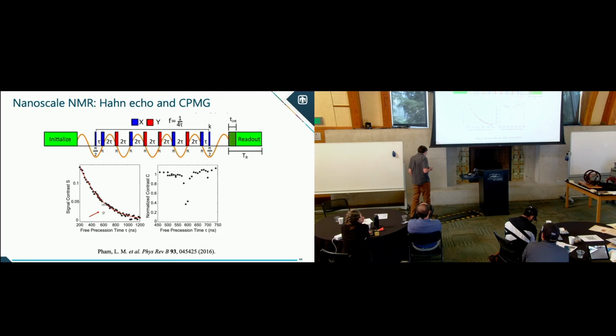Now, often people in the qubit community will use this, it's called dynamic decoupling, to actually decouple from noise. You want to get away from these specific noise sources. With sensing, we actually use that to detect nuclear spins. In this case, this is the intensity of the Hahn echo, or a CPMG sequence, as a function of this tau precession time. You get a standard T2 decay, but then you get an extra decoherence here. In this case, this was actually specific to the nitrogen spin. So we were sensing just the nitrogen within the material.